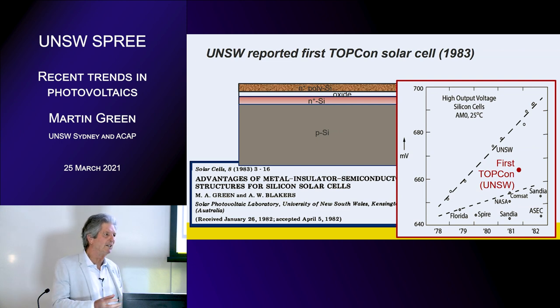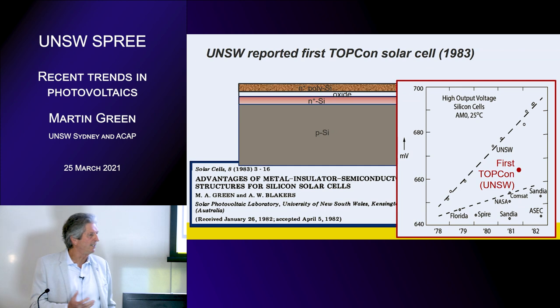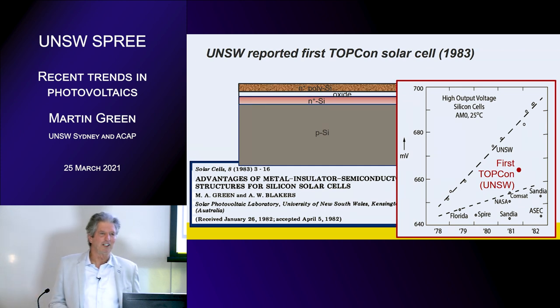So we were looking at that because we were working on tunneling metal insulator semiconductor, and the problem there was the metal would react with the oxide if you heated it above, you know, 300 degrees or something or other, you're very likely to short out the tunneling contact. So we were working on polysilicon as a way of overcoming that and got quite good results, as you can see on the chart on the right there.